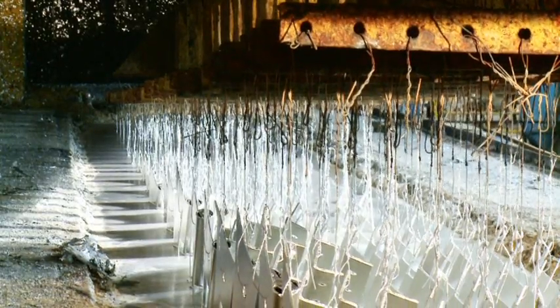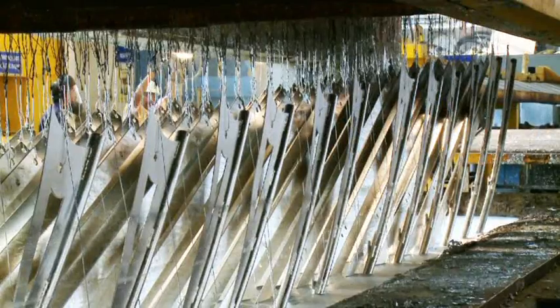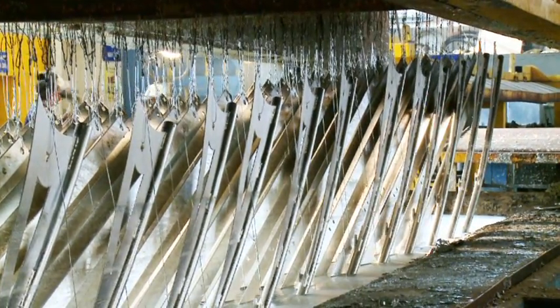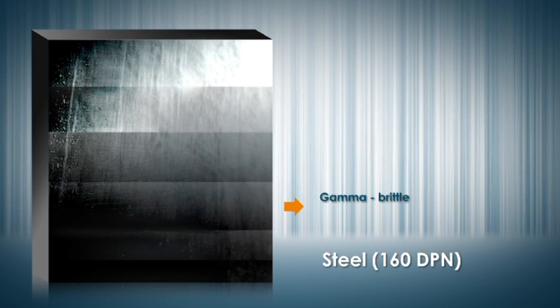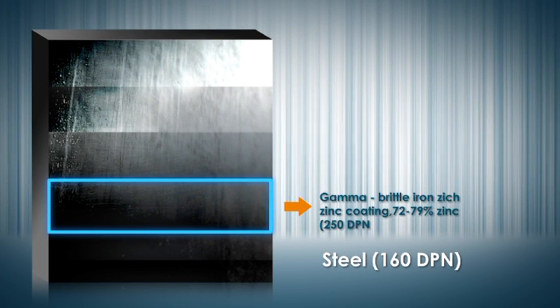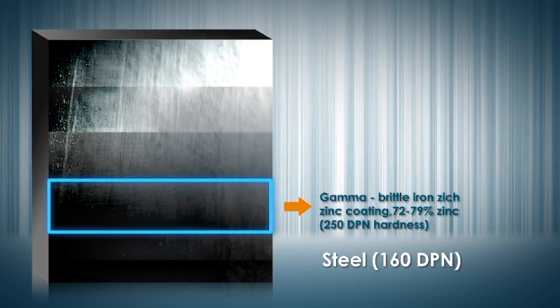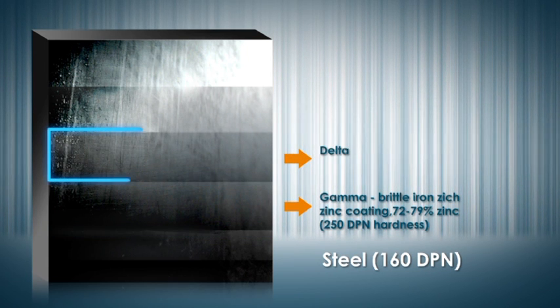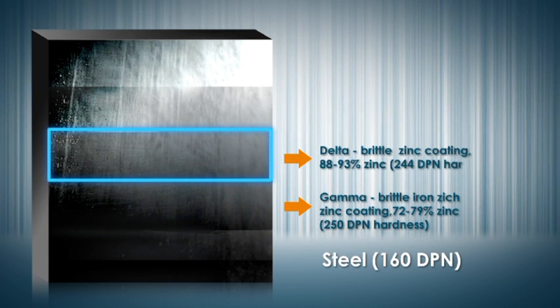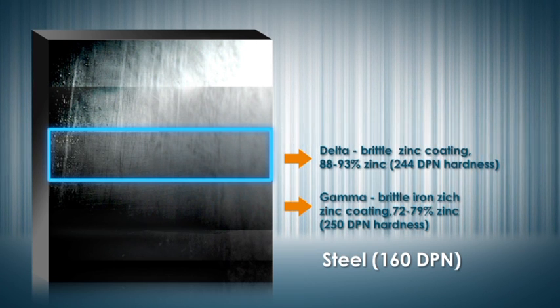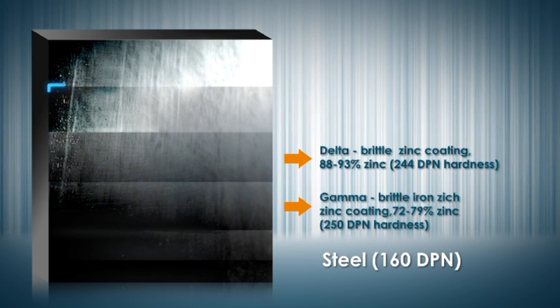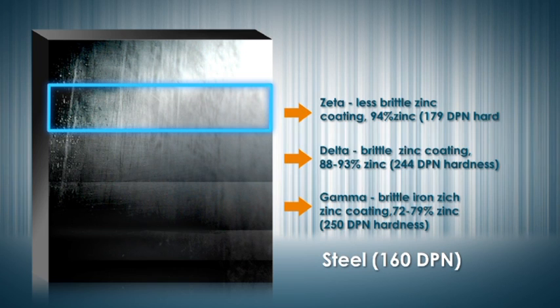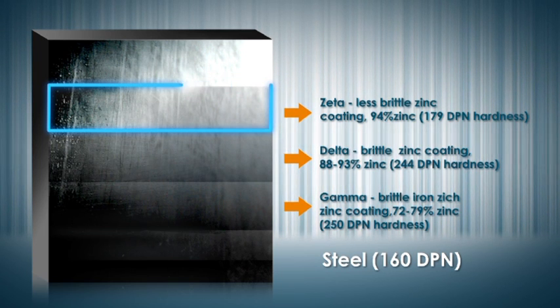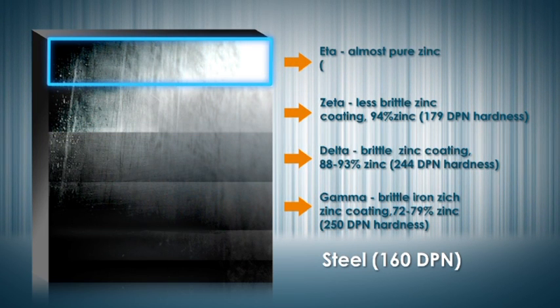Once this is done, immediately a metallurgical alloy is formed between zinc and steel, which results in a thin molecular layer of brittle, hard high-iron zinc alloy called the gamma layer. Next, a much thicker, hard brittle alloy layer is formed, which is called the delta layer and contains 7 to 12% iron. On top of this, the zeta layer forms, containing about 6% iron, and finally the surface layer, which is virtually pure zinc, called the eta layer.